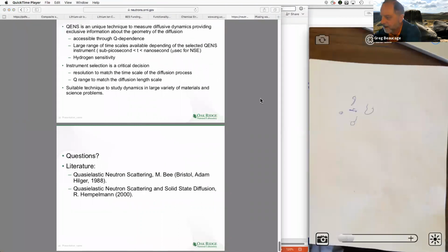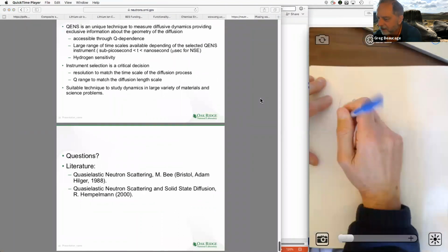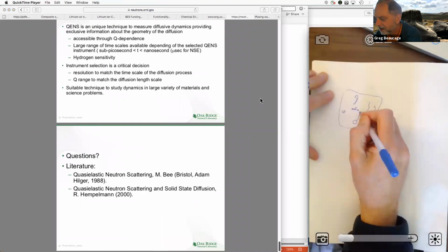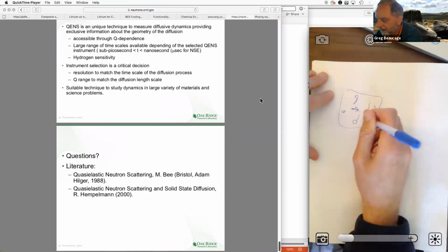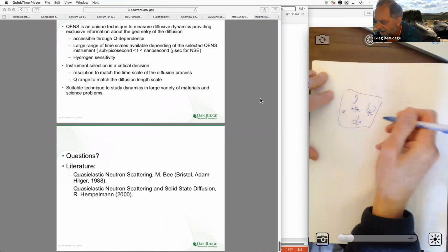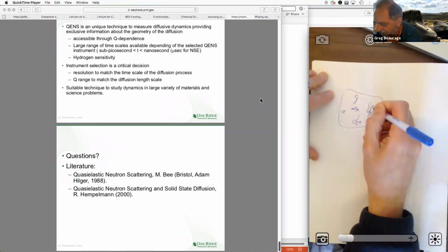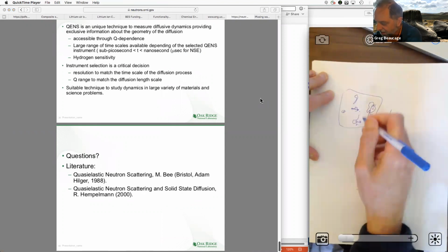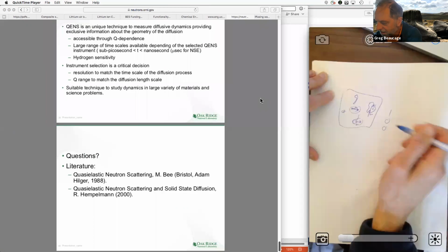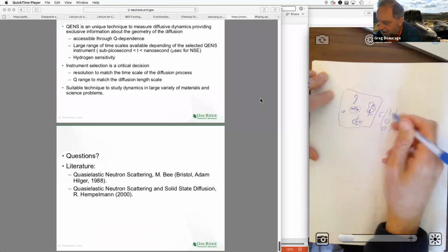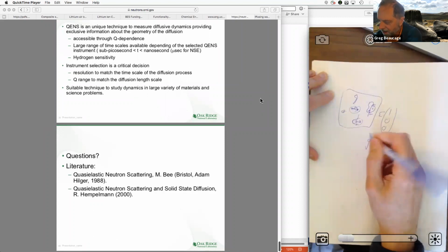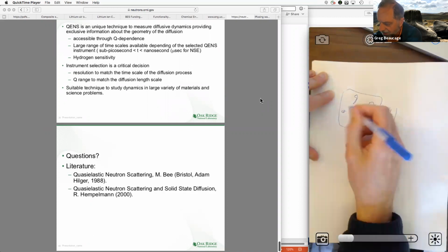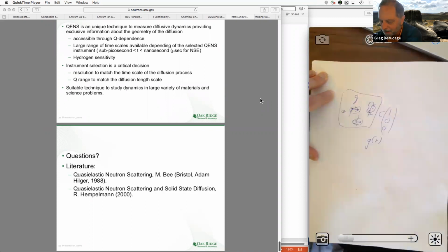So you have your material, some field of view, and then you're going to throw darts, meaning you put an arrow into the random structure. They're all the same length r, and sometimes the two ends are both in the phase, and that counts 1. This counts 0, this counts 0. You sum up all those conditions and get a normalized function. If r is 0, then it's 100% that both ends would be in the particle.